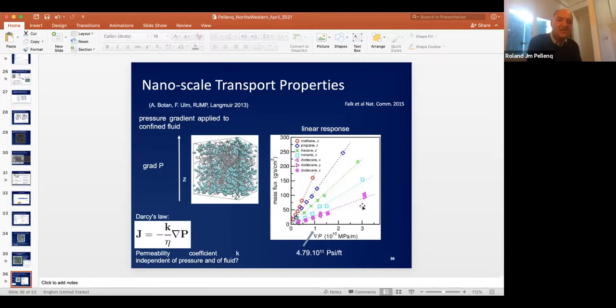K, which is the permeability, is expressed in meters squared. So this is typically a geometrical thing. It's really a characteristic of the porous material. The eta at the denominator is actually the viscosity, which is a fluid characteristic, right? That we can calculate or get from data. Anyway, if we apply this pressure gradient and we plot the flux as a function of this pressure gradient for the different molecules, what we see is that we do have a linear response theory. Yes, we're still in the linear response theory. Very good. Meaning that the flux is proportional to the pressure. So there is a constant there, and the constant is K over eta. Very good. Okay. So let's calculate eta from statistical physics.